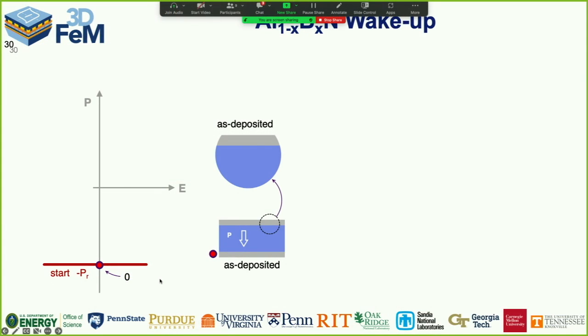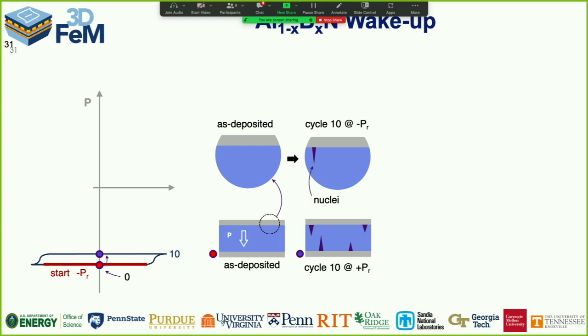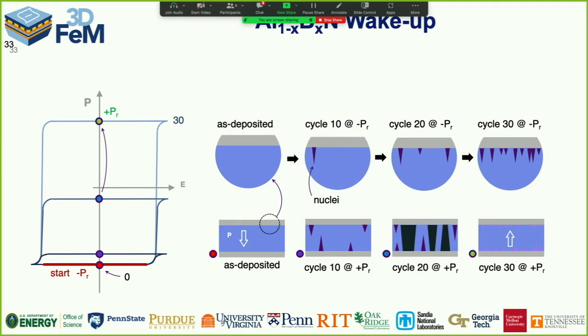You run the first hysteresis loop, and it behaves like a linear dielectric. So a very small change. The slope on that is simply the dielectric constant of the solid. When we field cycle it, we believe that we are adding nuclei of oppositely oriented polarization into the material. Once we have them there, they're hard to get rid of. And each of these nuclei can only sweep a finite volume in the time that we give it for polarization reversal, which means that I need more and more nuclei before I can get the entire hysteresis loop to wake up completely.